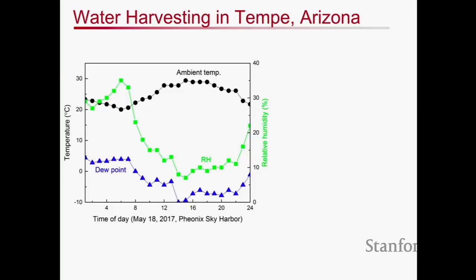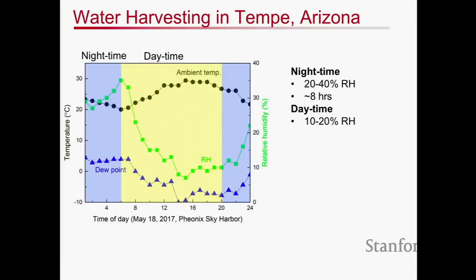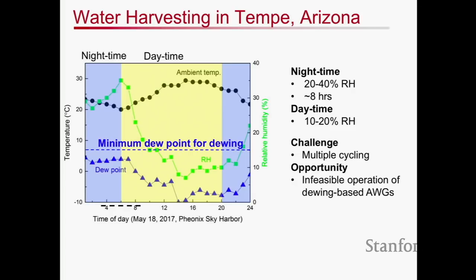So we moved forward to taking this kind of design to Arizona with a few improvements. The key here is that in this more arid condition, the nighttime humidity is about 20 to 40%, and the daytime is still relatively low. The dew point can also be relatively low and even negative in this case, right? So this becomes very challenging for dew harvesting type technologies.